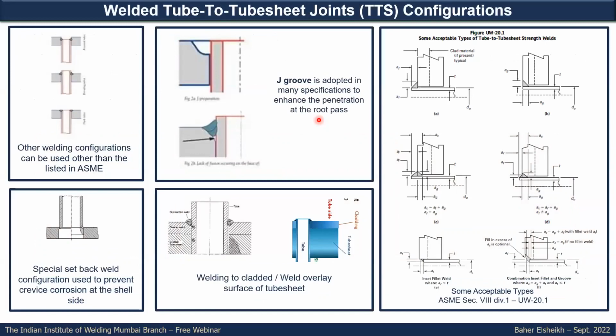Those are some of the common or accepted configurations of the tube-to-tube sheet joint. To the right here, we will see this is from ASME Section 8, Division 1, UW-20. These are some of the recommended shapes or configurations of the welded tube-to-tube sheet joint, whether by fillet weld or by groove, or by a combination of groove and fillet weld, whether equal size or different size. But other than those recommended in ASME, you are not restricted to use only the ASME configurations. There are some other configurations, like what you can see here, different configurations, or like this one, where you have some setback